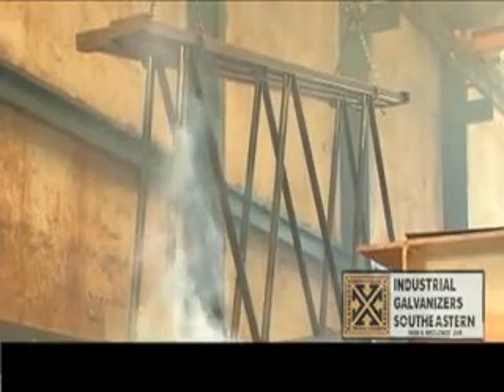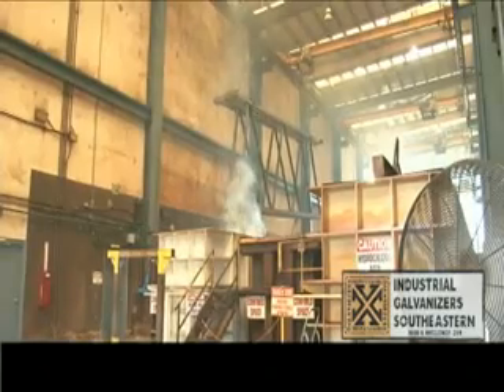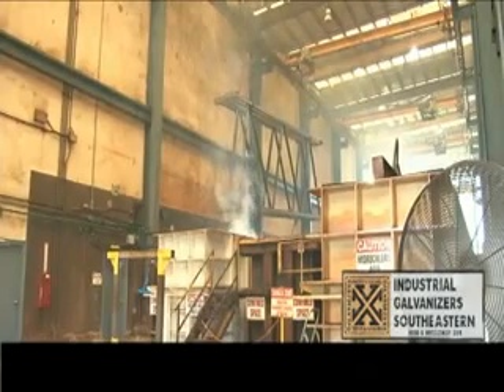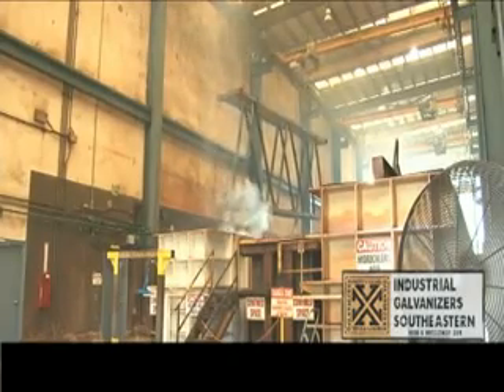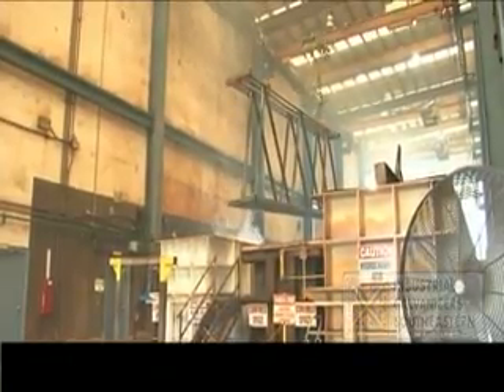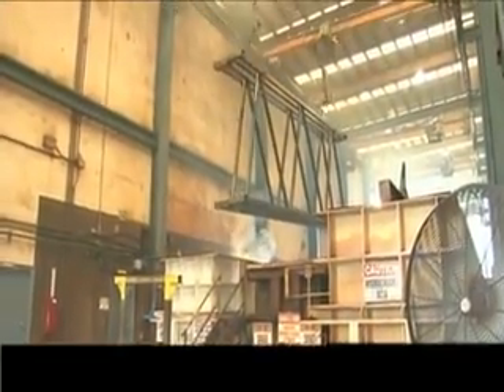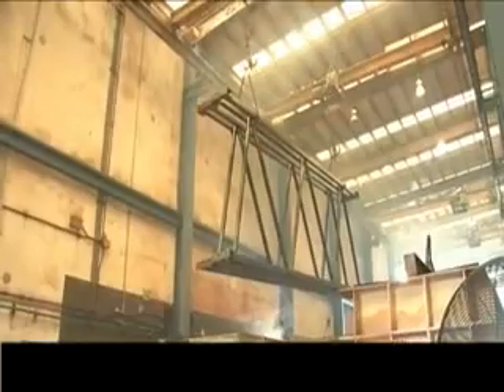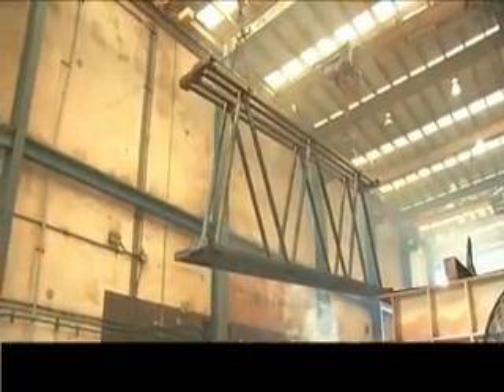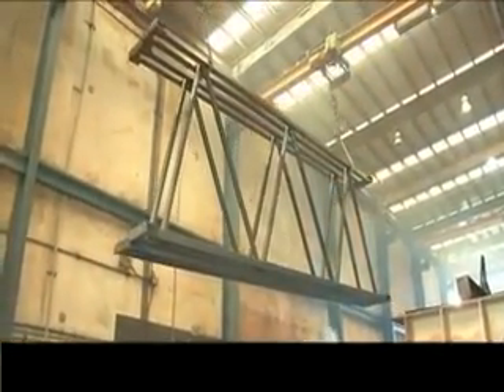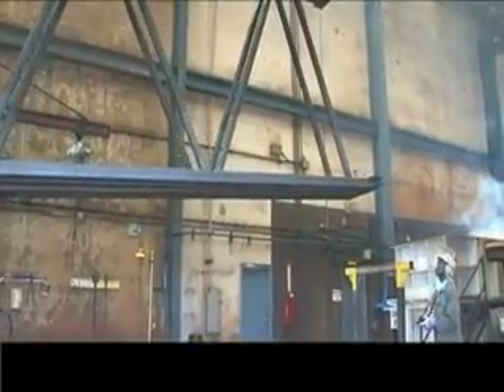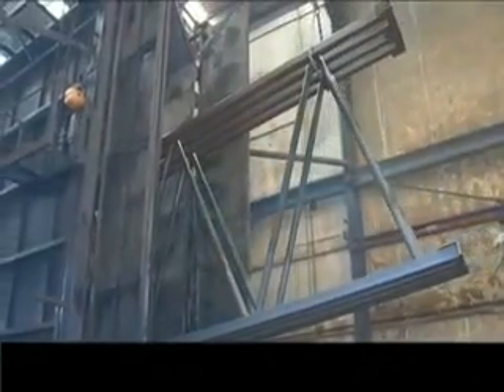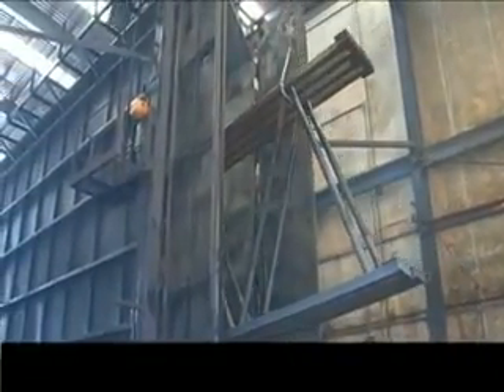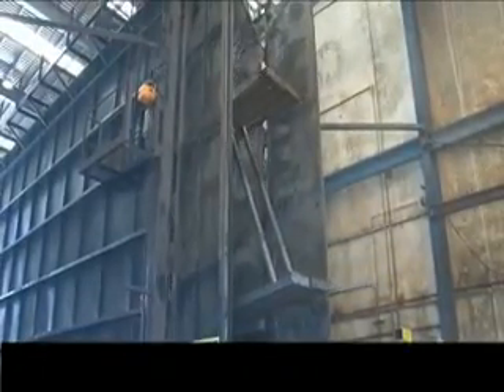The first process, the trusses are dipped in a solution to remove soft oils, then a rinse tank. And the next step is a hydrochloric acid tank, which pickles the steel and gets rid of all the scale, rust, and other contaminants on the steel. This is followed by another rinse, and then a pre-flux tank, which is shown here. Now that the bare steel is totally prepped, it's ready to be transferred to the galvanizing tank. This tank contains molten zinc plus additives, heated to 840 degrees Fahrenheit.